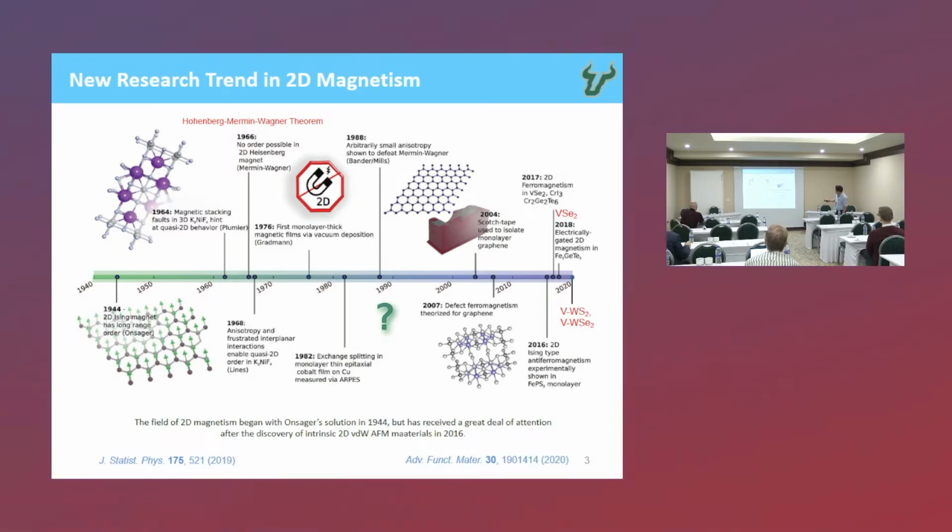So in this talk, I will focus more on this one because people use FGT as a material and create heterostructures based on it. However, both the VSe2 and also the FGT are metallic. So that's why there is a limitation for the optical response, which is only open to semiconductors. And therefore, in 2020, we made another discovery where we show that it's possible to create a new class of 2D dilute magnetic semiconductor based on magnetically doped transition metal dichalcogenides. In this case, the vanadium-doped tungsten disulfide and tungsten diselenide.